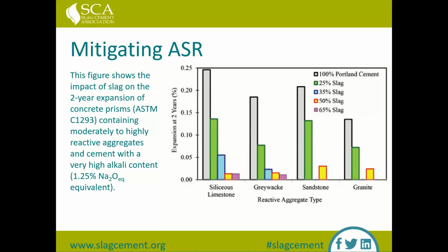Here we've got a graph showing just how important slag can be in mitigating ASR. What's shown is C1293 test results with 4 different reactive aggregates. We can see the tall gray bar being the all Portland cement mix, and then we've got increasing slag amounts of 25% up to 65%, and you can see the expansion due to ASR, how that reduces as we increase the slag replacement levels, from high expansion at 100% Portland cement down to very, very small amounts, especially when we get up to 50 and 65% slag. Very, very little expansion. This is really showing the effectiveness of slag in mitigating ASR.